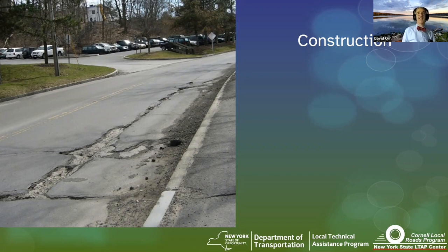I watched them. All three of them used the same pavement maintenance technique, throw and go. They just threw patch in and drove away. And in all three cases, it failed within 24 hours. And you can see the patch along the side of the roadway here. Okay. That actually is, in my mind, a construction failure. So keep that in mind.